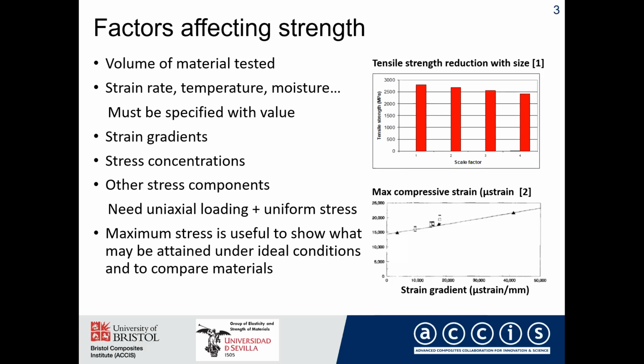Of course, it's well known that stress concentrations and other stress components may be present in a test and clearly can affect the result. And you need uniaxial loading and uniform stress, which is easy to say on a slide, but not so easy to achieve in practice. But nevertheless, despite these caveats, we would argue that the maximum stress is still useful to show what may be attained under ideal conditions and as a basis for comparing different materials.